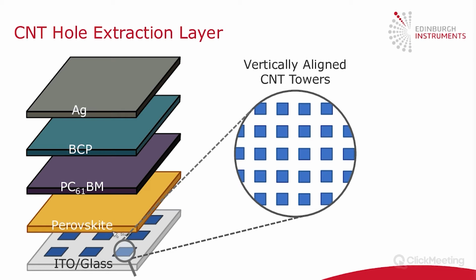And you typically do this with the aid of other layers to pull the electrons and holes out of the perovskite. So here we have PCBM to pull electrons out towards the silver electrode. And in this paper, they were looking at carbon nanotubes to pull the holes out. And we want to investigate how good these carbon nanotubes are at extracting holes from the perovskite.